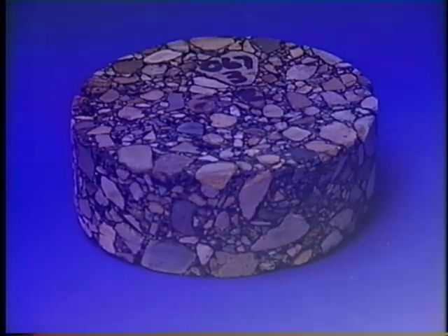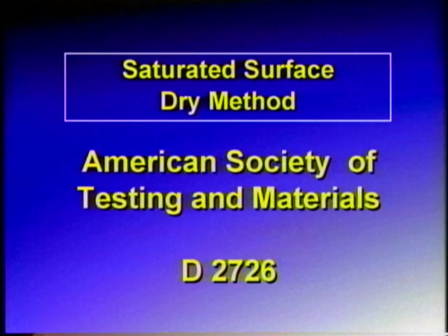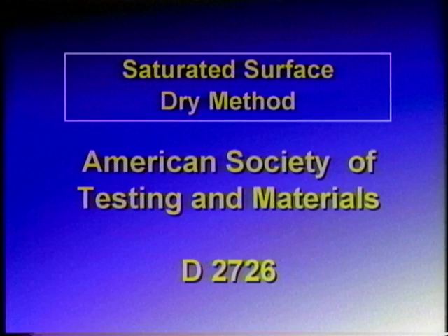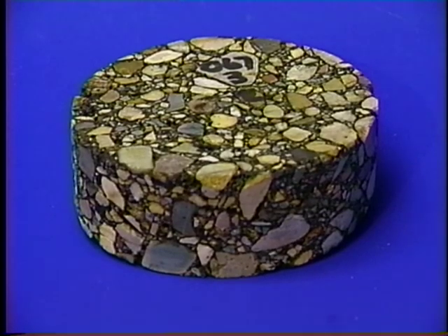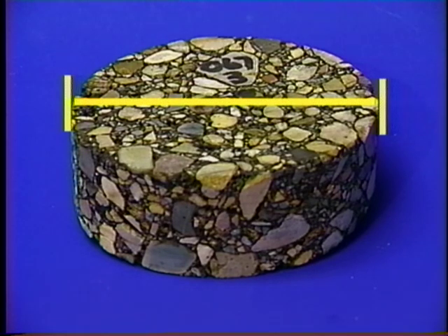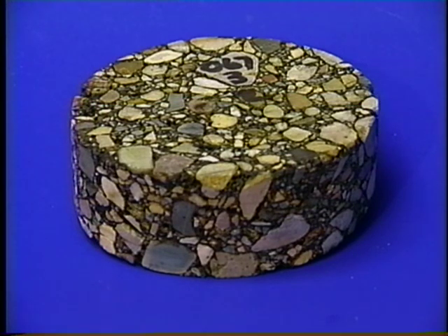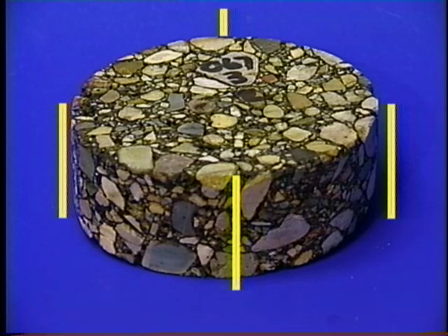The standard procedure for determining air voids is the saturated surface dry method, specified by ASTM D2726. After the percentage of air voids is determined, measure the diameter and thickness of the samples. To measure the diameter of the sample, measure two points that are at 180 degrees to each other. To measure the thickness of a sample, measure four points that are 90 degrees apart and calculate the average of those points.